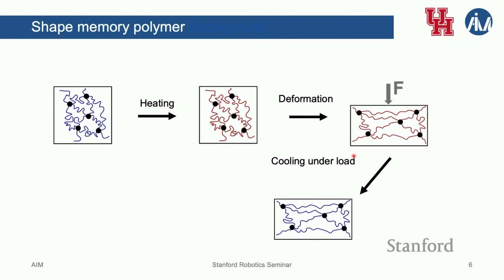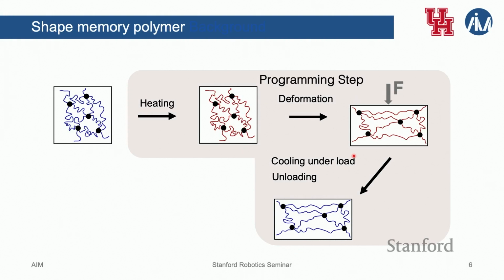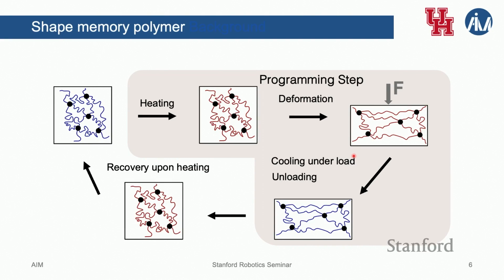And now, because it transitioned back to the glassy phase, the Young's modulus increases significantly, and it cannot recover to the original shape anymore. So we can unload our mechanical loading force and just let it be, and it will stay in that deformed shape at a cold temperature. And this whole process we call programming. So now, that's the programming step, right? Now we have the shape by itself without any constraint in the deformed state. And the last step is the autonomous recovery. So if we heat this back up again, it will recover back to the original shape without any human assistance.